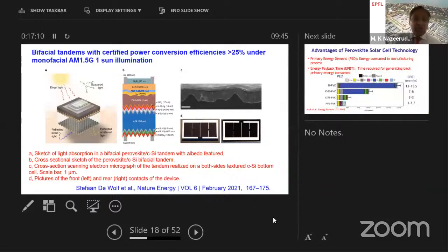Stefaan De Wolf is the senior author. He has taken the bifacial silicon solar cell, again deposited nickel oxide. In the previous case, it was a self-assembled monolayer, and now here it's an inorganic hole transporting material deposited on top of the bifacial silicon solar cell, followed by perovskite material, electron transport material, and the cross-sectional image is shown here.